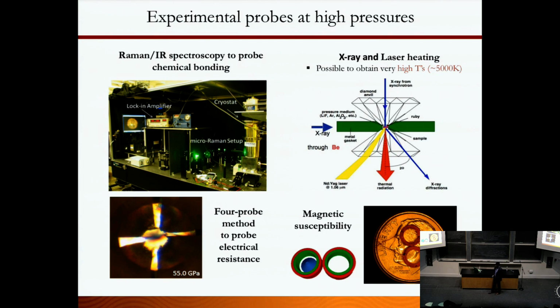Or also you can use magnetic measurements. This is the size of the coil we used. I just put it in here so that you can have an idea of its size. These are just small samples, so you have to make sure that you have enough filling factor. You make those coils very small and sit around this diamond area right here. So if you have a superconducting transition, we can do magnetic measurements.